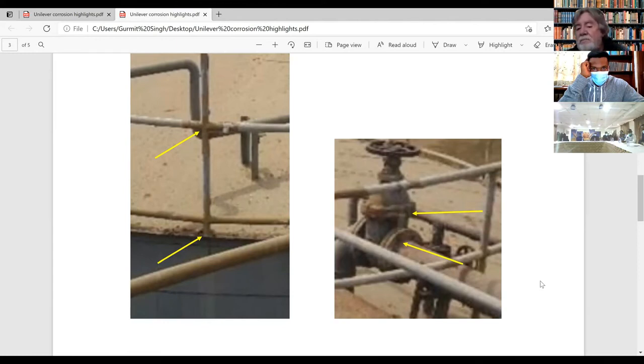So when you're blasting these areas, if that valve is not going to be unbolted and taken apart, it's going to be left as is. When you're blasting, you've really got to focus inside the two plates where they bolt together. Put your blast nozzle inside there and hit the top and the bottom all the way around the whole flange. And you put the Zinga in there with a brush, okay? Normally with these sorts of things, I say you take a normal paintbrush and you cut off the last 20 millimeters off the brush. That makes the brush very stiff. So you dip it in the Zinga and you just ram it in. You don't go all soft. You hold the brush this way and ram it in there all the way around, and you force the Zinga inside there. That changes all the dynamics inside that joint, and you'll never have crevice corrosion inside that joint.